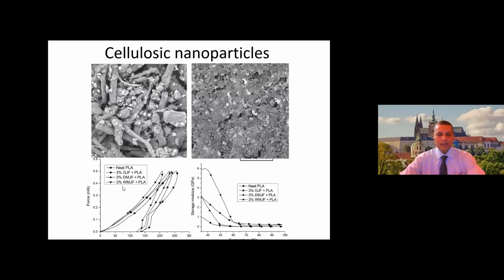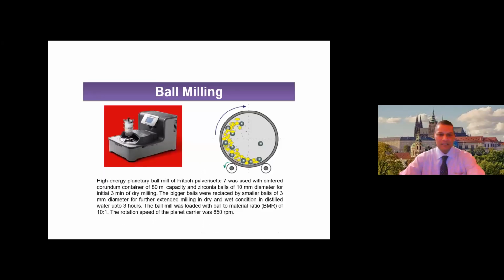And to be noted that the nanoparticles used in such composites are limited to a very small percentage by weight, as high as 5% maximum. And at the same time, they are able to cover the whole volume of the material very efficiently because of their minute size. So it is not that 3% is too small, but they occupy the whole space, efficiently increasing the specific surface area and the performance thereby.